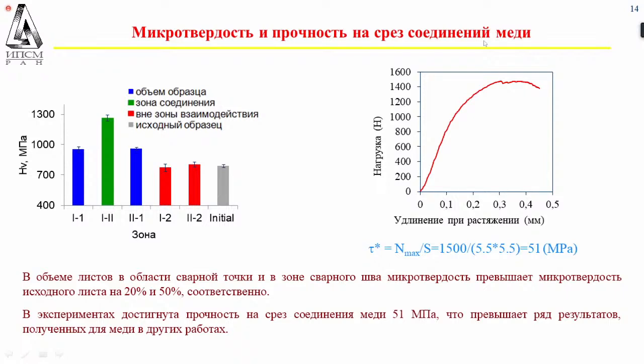We can also see the cut of copper joints, and in the area of the welding seam, we can see about 20% microhardness, and the microstrength is about 1.5 times higher.